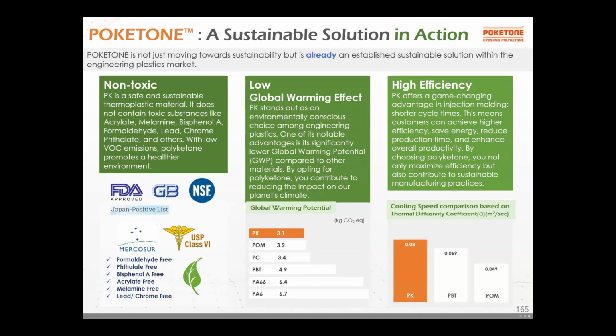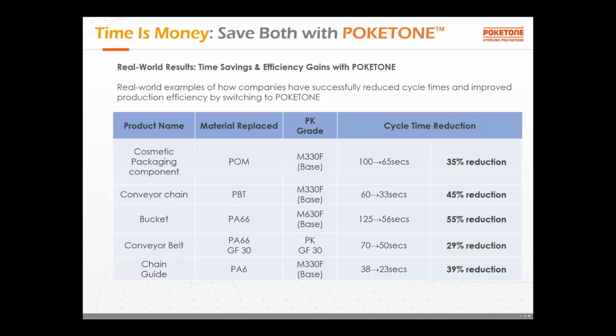Another thing is that the polyketone has a higher thermal diffusivity coefficient. So as I talked to you before, you can reduce the total cycle time. And this is the example of the real application. We reduce the cycle time by reducing the cooling time. The example is the POM, PBT, and polyamide replacement from 29% to over 55%.